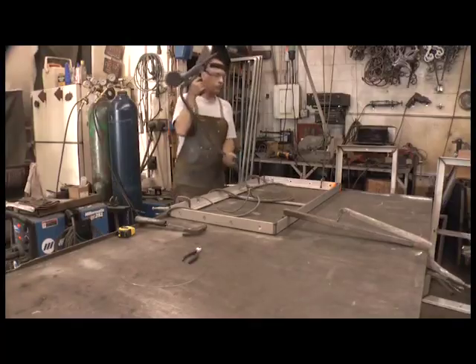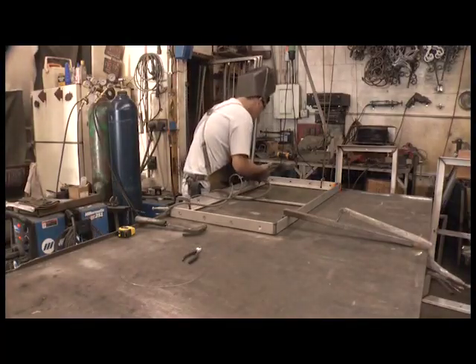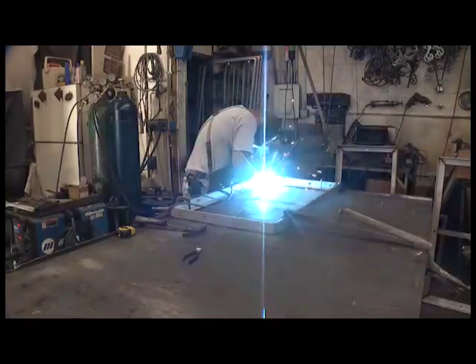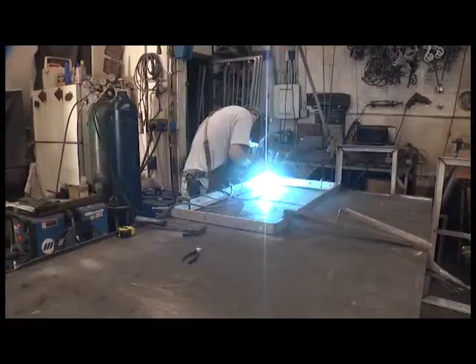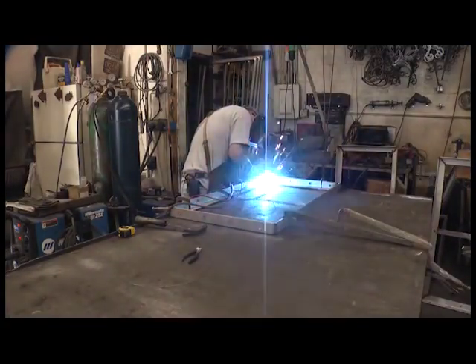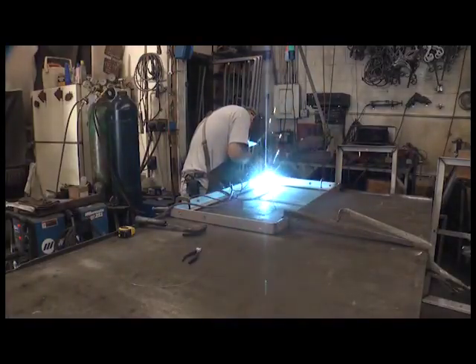Two vertical down welding passes were performed on each joint. The first, or the root pass, was run fast and straight down. This filled the corner and helped maintain the length of the wire stick out, which affects the characteristics of the welding arc as the second pass is weaved down the seam. The back and forth weaving motion was used to increase the width and the buildup of the weld bead. When the bottom of the vertical was reached, the weld continued on along the flat portion of the joint.